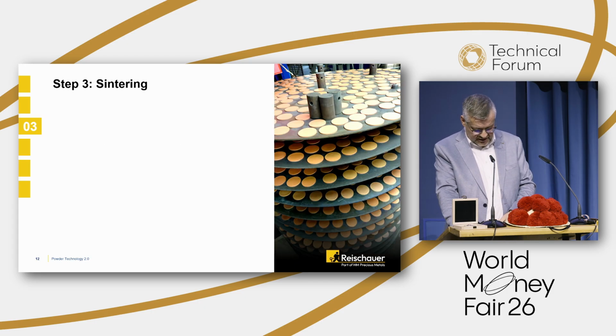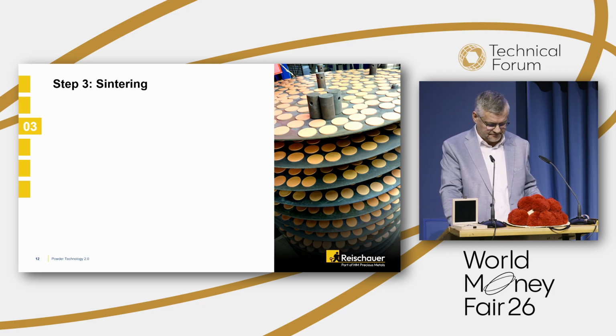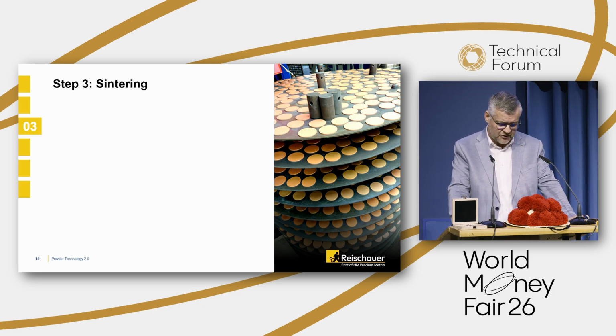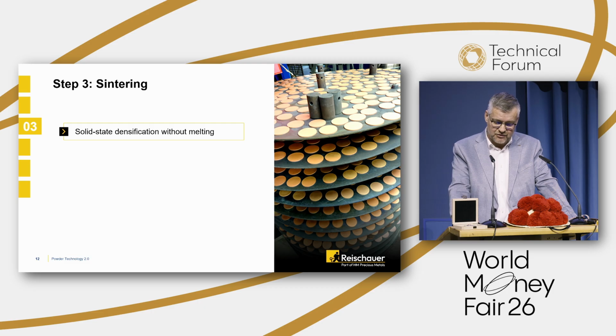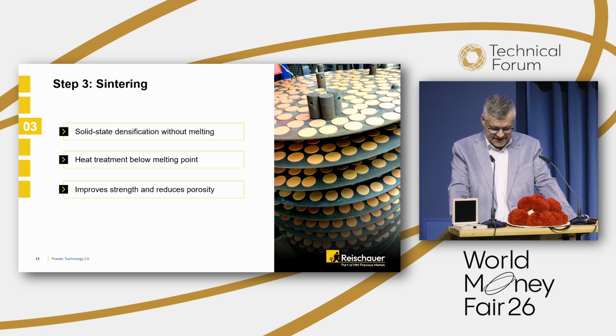The final step which you need to remember is the sintering. This is a thermal densification process carried out below the metal's actual melting point. During sintering, the blanks shrink slightly, becoming compact and highly dense, and any remaining porosity is closed. With proper execution, these dimensional changes can be calculated very accurately, with less than 0.001 millimeters of deviation.